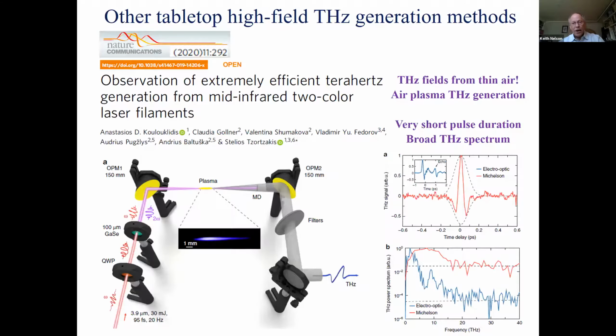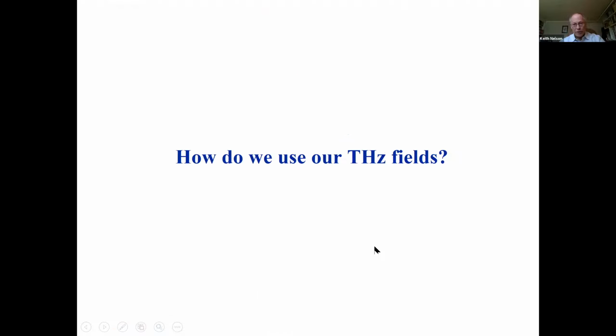There are some other ways, and there are other crystals, I should say, that go out to higher frequencies than what we've generated. Another way to do that is you can actually generate terahertz fields right in air. Femtosecond optical pulses can ionize air in a way that sends the electrons all in one direction. There's moving charge, it radiates, and that can be very short. Here's a single cycle pulse that's just 1/10 of a picosecond. Here's the spectrum. It goes out almost to 15 terahertz. So the whole terahertz region is accessible with quite strong fields.